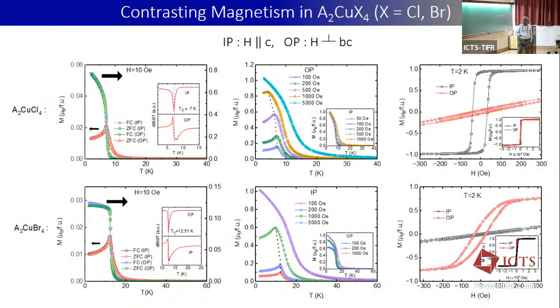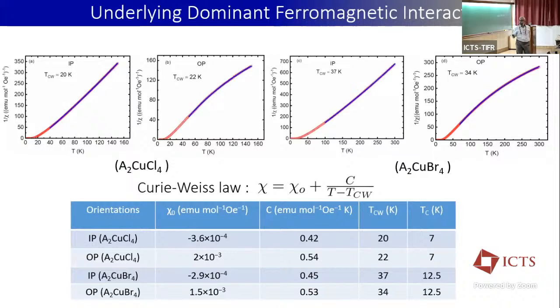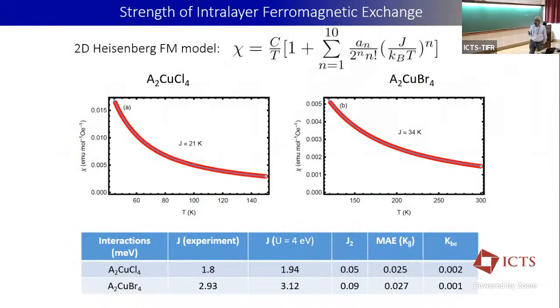So what I'm trying to understand is why this magnetization changes when you change from chlorine to bromine. Then we look at what could be the dominant ferromagnetic interaction. In both cases, it does not matter whether in-plane or out-of-plane, chlorine or bromine, because I told you these are quasi-2D Heisenberg systems, in every case we see there is a positive Curie-Weiss theta, and this tells that the underlying interaction is ferromagnetic. If the underlying interaction is ferromagnetic, then why should there be a downfall in magnetization along the out-of-plane direction?